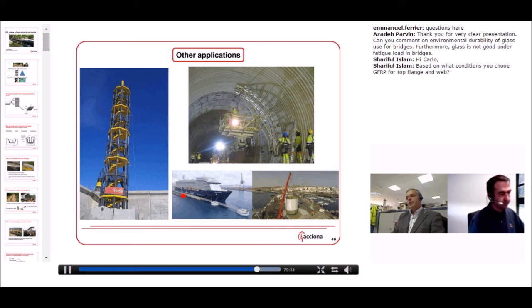GFRP is still much cheaper than carbon fiber fabrics, so you should try to use carbon fiber where it is actually needed. And as I told you, the design of the FRP girders is dominated by the service limit state of the girder, especially under sustained load. For this reason, we use mainly carbon fiber in the bottom flange in the longitudinal direction, and we use concrete to resist compression.